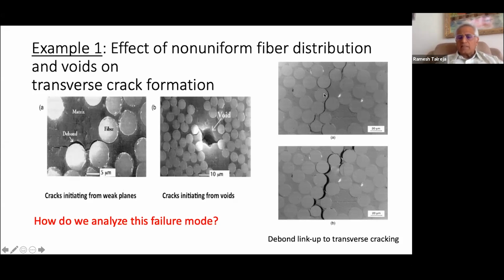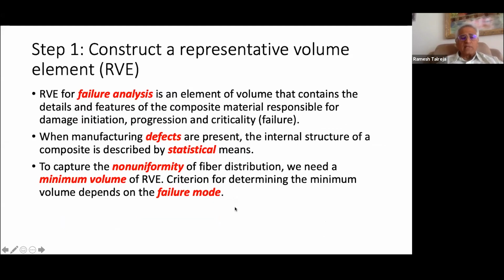Here are certain images that show you that this early stage that I pointed to develops into a full crack, and the evidence of that comes when you increase the loading, in this case horizontal. You see the thickening of that dark area, which suggests that on one side, the composite is separating from the other. So sort of a crack has formed here.